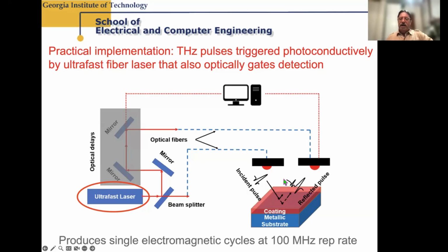We can measure the amplitude and phase of this reflected signal by adjusting the time delay of the detection beam path and varying it. In fact, by doing this experiment many times, millions of times, let's say, we can map out the reflected transient, its amplitude and phase in time. Then by analyzing that transient, we can, for example, in this case, determine the coating thickness on that metal substrate. And maybe if there's a defect between the coating and the metal, some inhomogeneity, we would see that as a different sort of signal in the region of the defect.